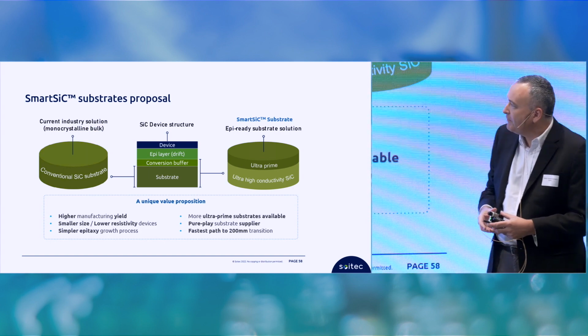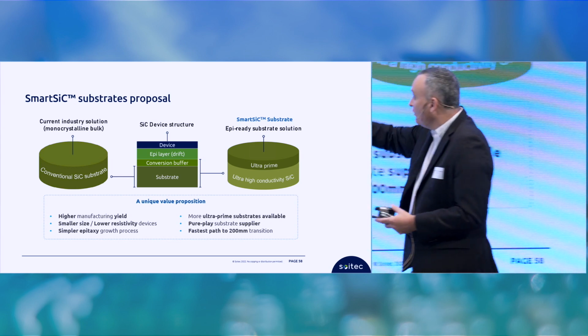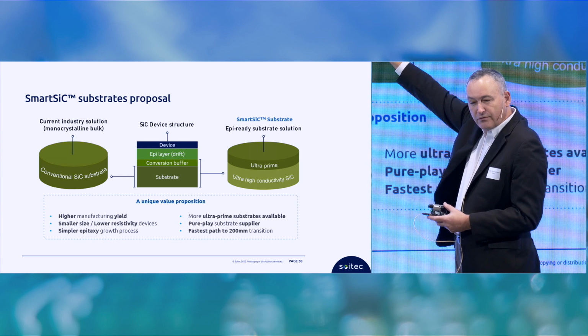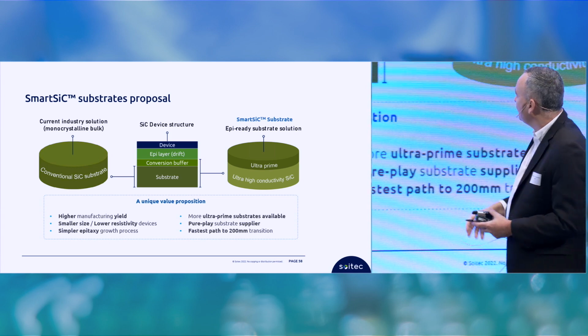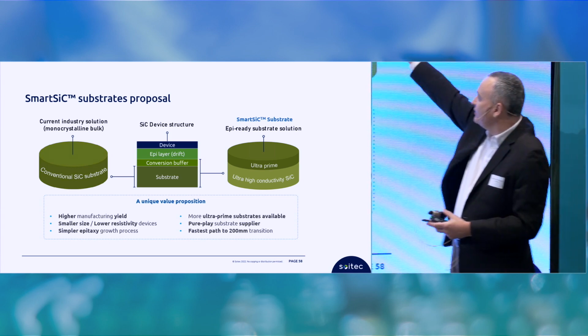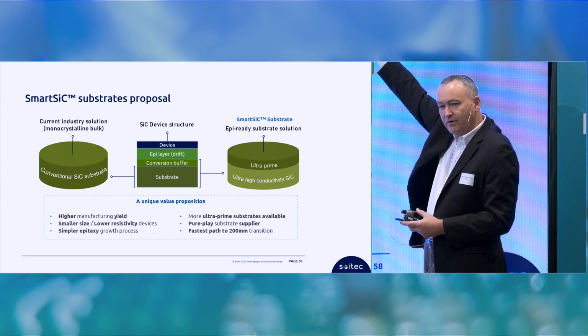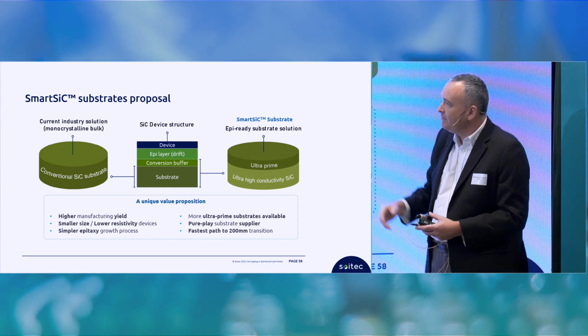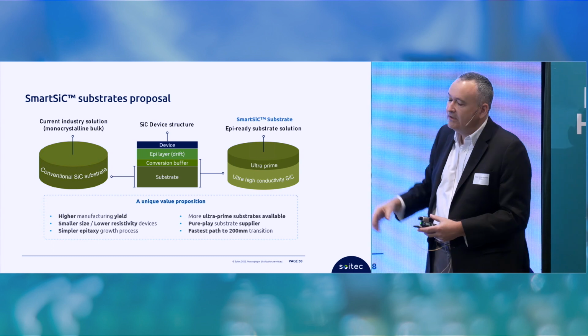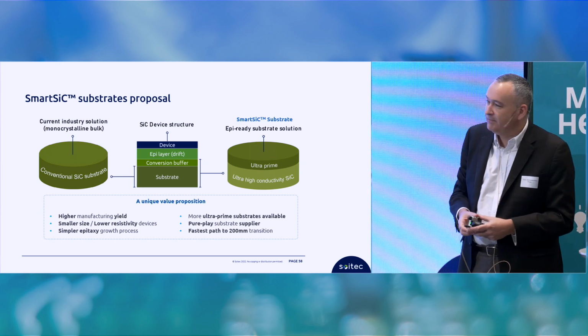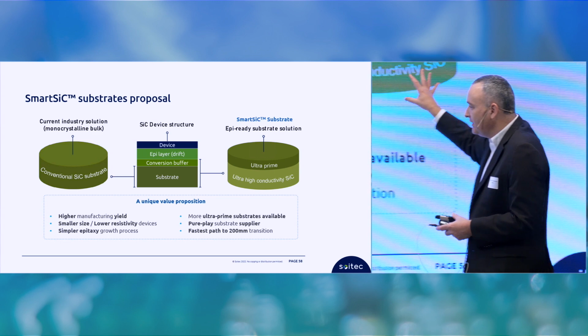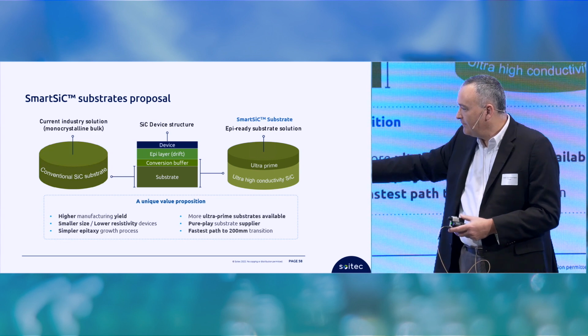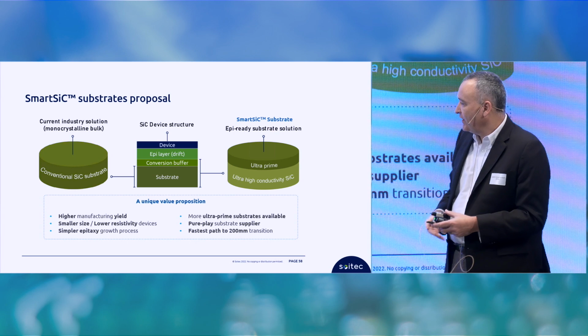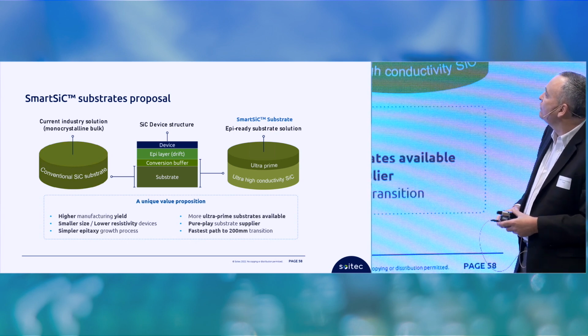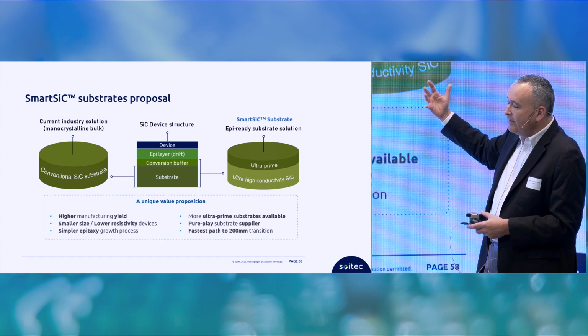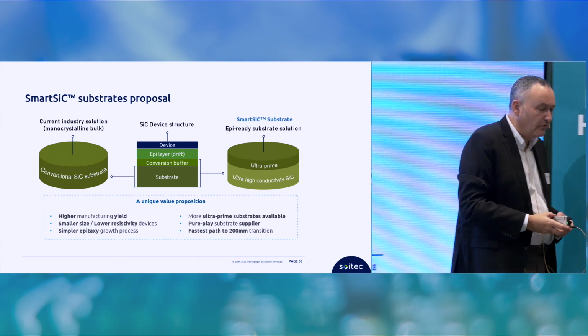If we compare with a bulk, when you buy a bulk SiC, you need then to create some conversion buffer layers, you need to create an EPI layer, then build your device. With SmartSiC, we will associate ultra prime thin layers supporting your EPI and device on the ultra high conductivity SiC product, typically poly SiC. So it will give a unique value proposition, improving the yield, improving the resistivity, simplifying the EPI process, and improving the adoption for 200 millimeters.